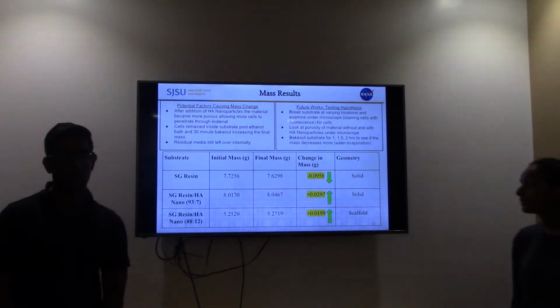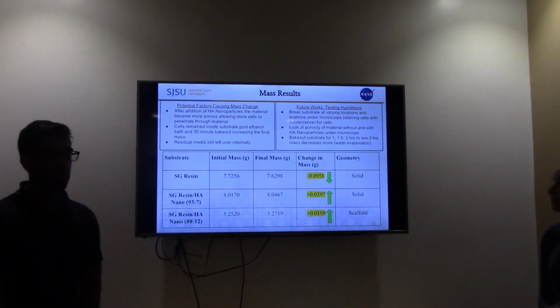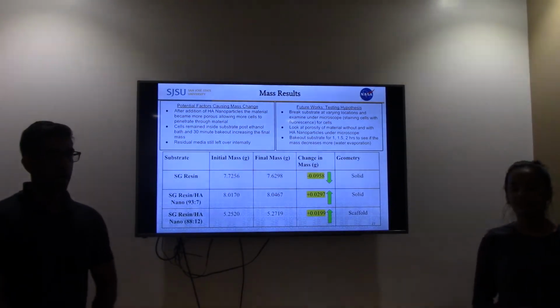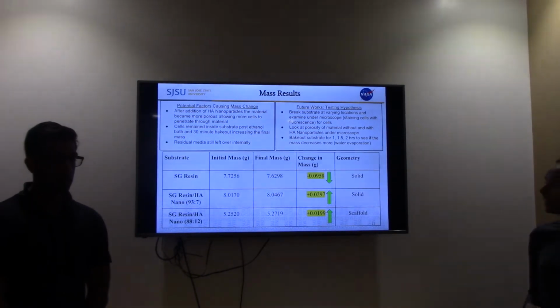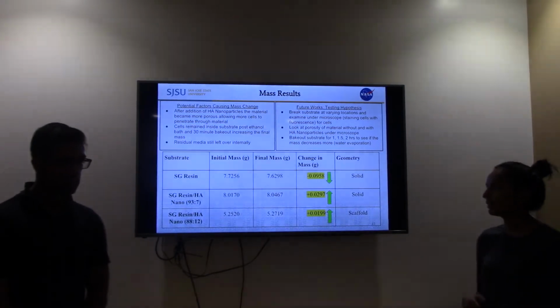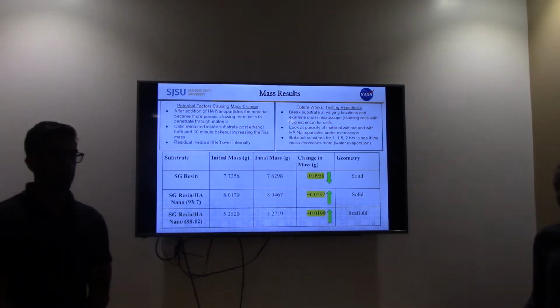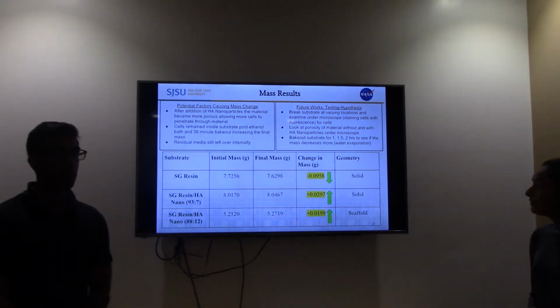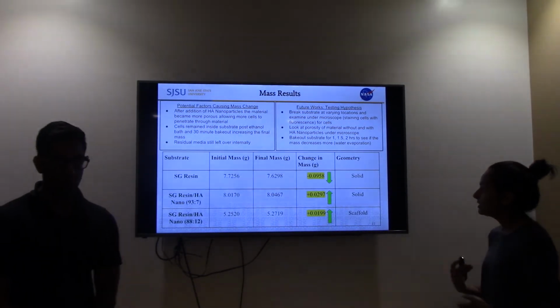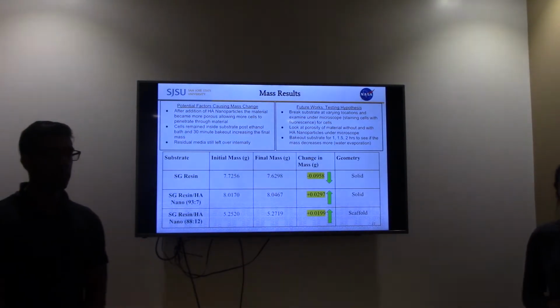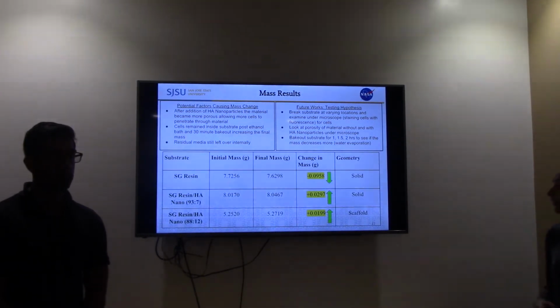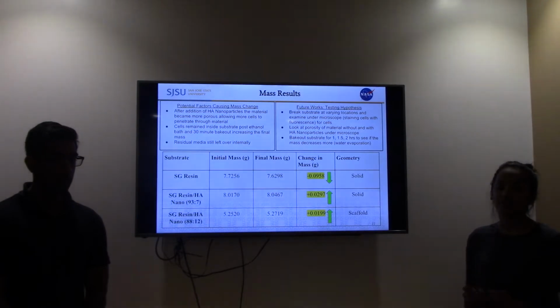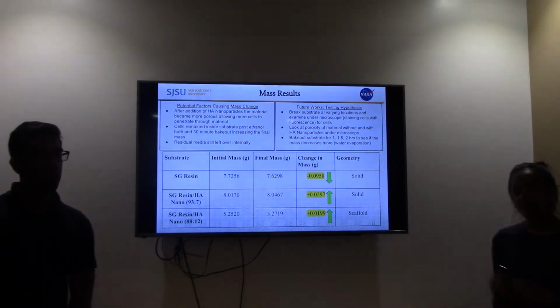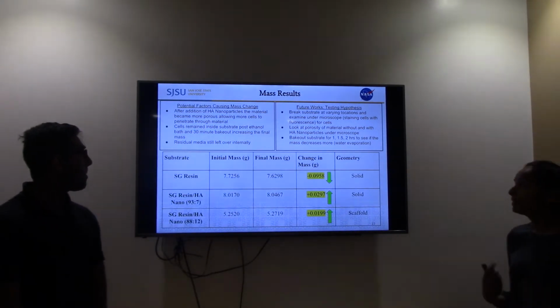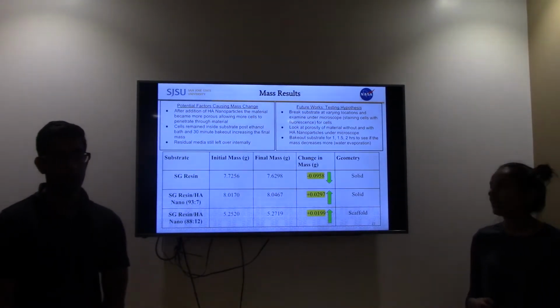For our mass results, for our SG resin by itself without nanoparticles post-experiment, we baked out our substrates in an oven at 120 degrees Fahrenheit for 30 minutes to remove any moisture from the media that was left over, and we wiped it down with ethanol. For the SG resin by itself, we saw a decrease in mass. However, for the SG resin with the HA nanoparticles, there was a slight increase in mass for both the solid and scaffold geometry.